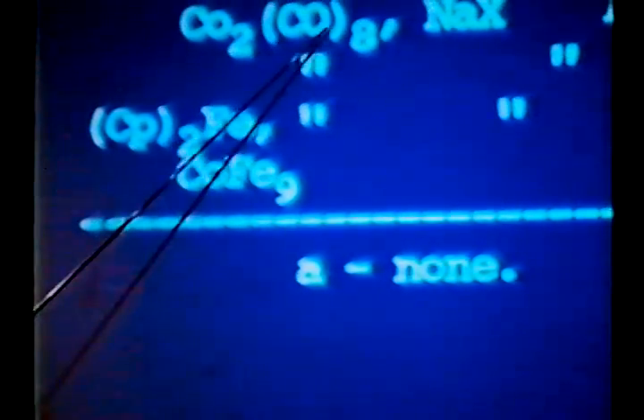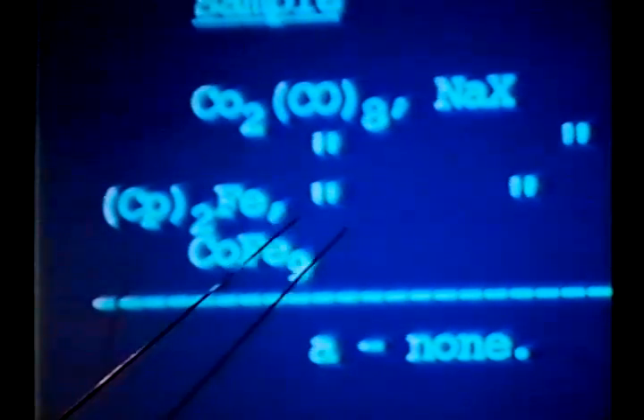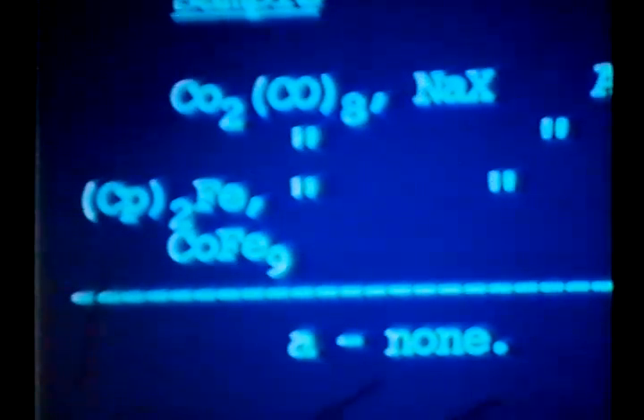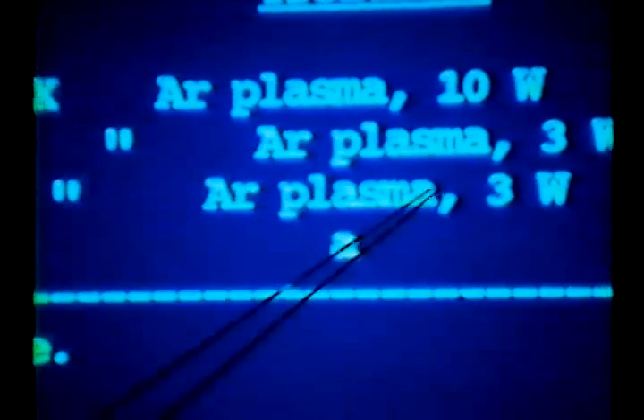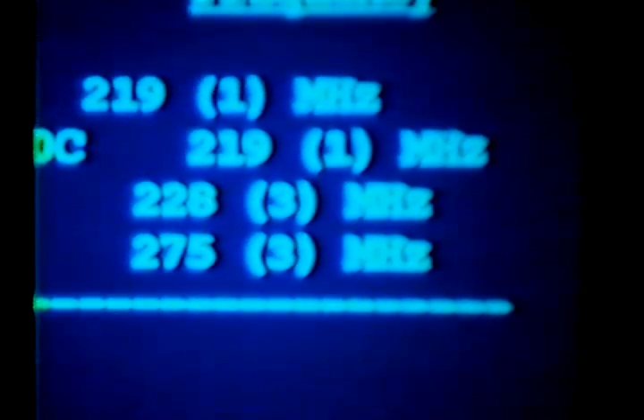But here's some other neat types of things you can do. You can co-adsorb two species, cobalt carbonyl as well as ferrocene, (C5H5)2Fe, and treat it in the plasma at 3 watts. And in this case, we get hexagonal cobalt. So by co-adsorption, placing an iron complex and a cobalt complex in the zeolite, we can control the structure of the resultant particle. It's fast, and it's a great technique to tell you that you control the structure as well.